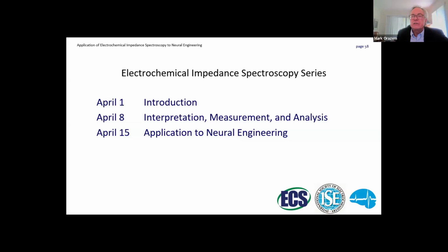If you use the Brug formula, you're assuming that there's a distribution of time constants along the surface. If you use what we call the power law model, you're assuming that there's a distribution of time constants through the depth of the film. You can use either one to calculate the capacitance from the constant phase element parameters. From that capacitance, you can estimate a thickness. If that thickness is in the ballpark of what you expect, that would be at least a suggestion that an oxide film is present. But if that thickness is on the order of millimeters, then you know that it cannot be an oxide film, or that your way of extracting capacitance has to be wrong.